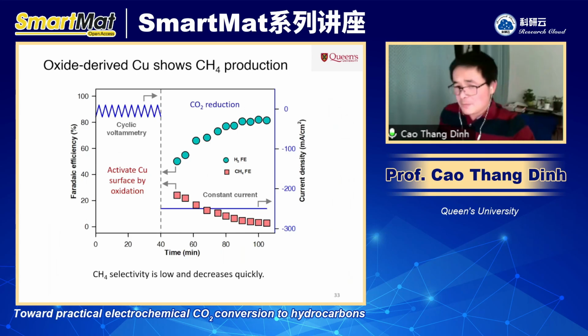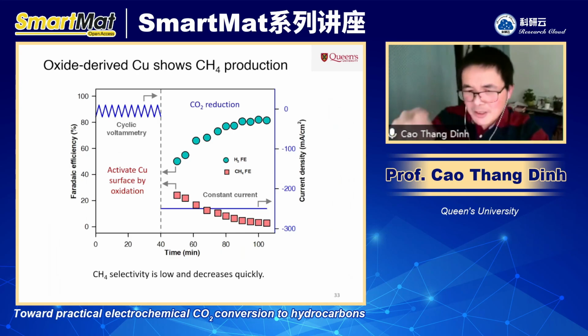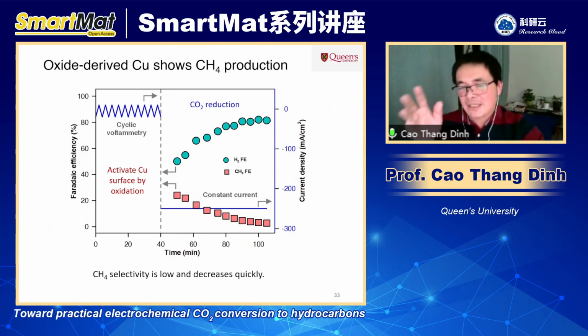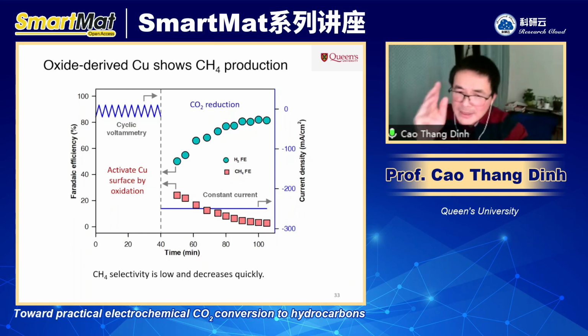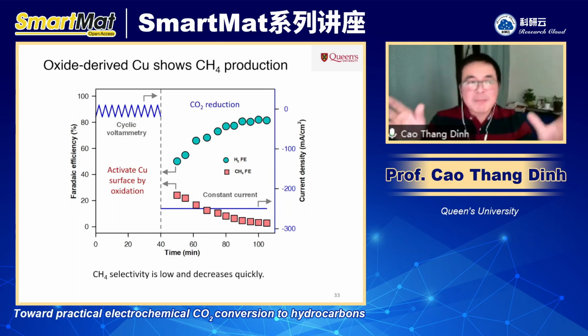Hydrogen goes down to about 50%, which is very positive. But the problem is that when you keep running the reaction, the selectivity goes down quickly. That's the challenge, and we don't know the reason. What we thought is that maybe we create something active, but because it's so unstable, the selectivity goes down quickly. If that is the case, what can we do?